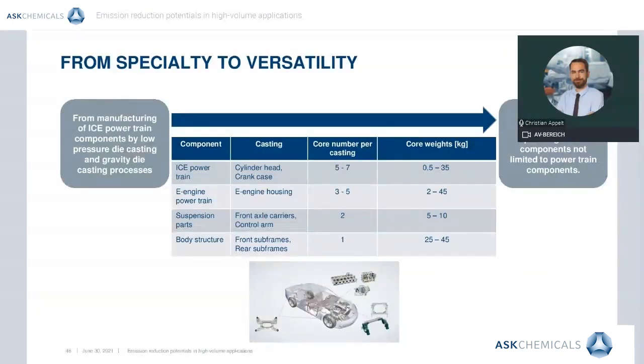Traditionally, the inorganic binder system Inotec has been utilized in low-pressure die casting and gravity die casting processes to produce classic ICE powertrain components, for example 4- and 6-cylinder heads and the corresponding crankcases. Nowadays, Inotec has matured to a much more versatile binder system, which is applied to a wide range of aluminum passenger car components, for example e-engine housings, suspension parts, and body structures. The difference to state-of-the-art ICE powertrain applications is characterized by a different number of cores per core package and varying core weights. While ICE powertrain components are based on core packages with different cores of high diversity concerning mass and geometry, suspension parts and body structures casting processes are based on just 1 or 2 cores with greater mass.